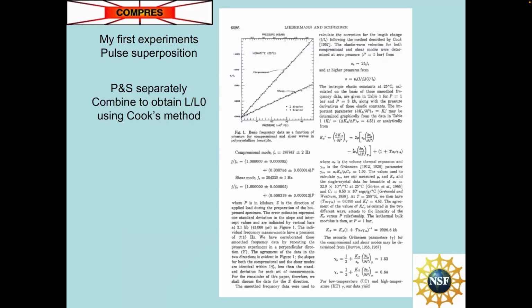is the first experiments I did using this technique. I measured the frequencies of both compressional and shear waves as a function of pressure to 3 kilobars, 0.3 GPa, for hematite at room temperature. Now, these measurements were done in a liquid medium apparatus, and of course, we had no idea how to measure the change of length. But Cook had developed the technique some years before, which is summarized in these equations, that allows you to use the travel times for both compressional and shear waves and combine them to give you the length changes that occur across this pressure regime, but still only at room temperature and only a direct measurement of length. The next